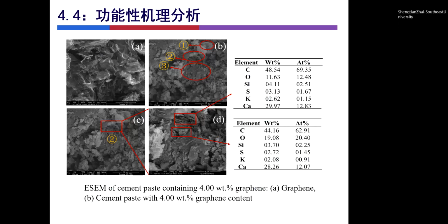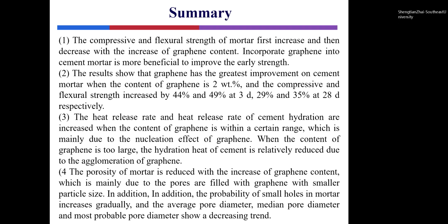To better understand the mechanism of the graphene in improving the strengths of the cement-based materials, we have to measure the ESEM of the plain cement and the cement with 1% graphene. A lot of the graphene laminar structures are distributed in the hydration products of the cement, which not only fill the pores, but also make the structure of the hydration products more dense. According to the experimental result, the summary is as follows.